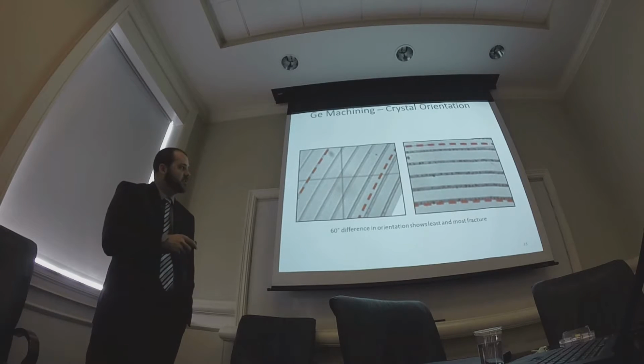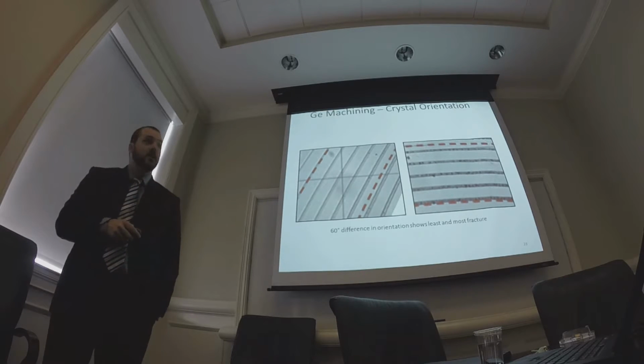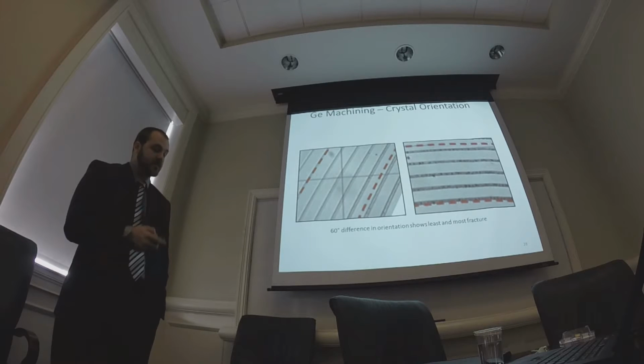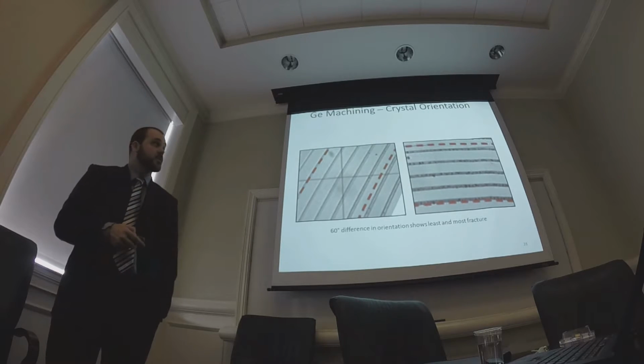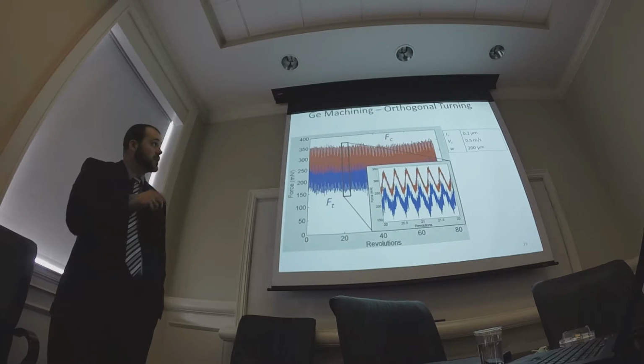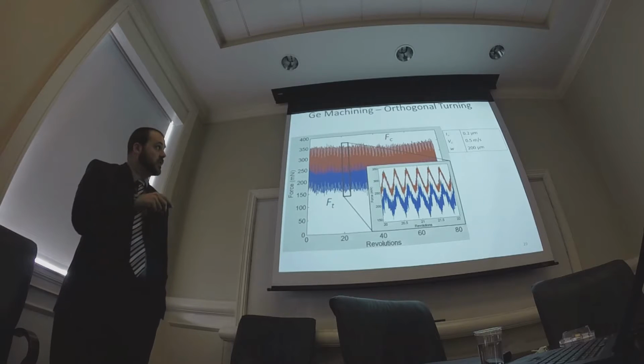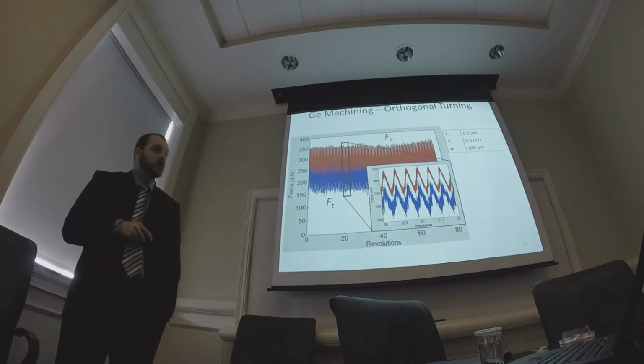No fracture, we start to see a couple little pits here, but we see significant fracture showing up here. This was about 150 to 200 nanometers different in maximum cutting depth, or chip thickness, just by changing the crystal orientation. So when I look back at the orthogonal cutting, I averaged all of this to get one data point. But if you come back and look at it, what's actually happening is this crystal orientation, and we're getting a pretty big percentage of force change just due to crystal orientation.